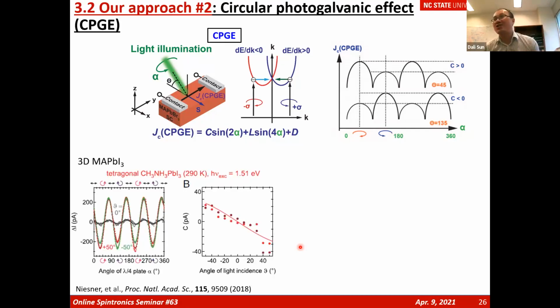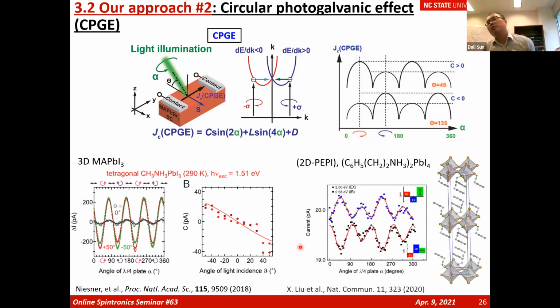And people use this method. Actually, the same author published in the PNAS publication in 2018 and demonstrated there is a possible split state in MAPbI3. They call it the Rashba circular photogalvanic effect. And Utah's group, Valy Vardeny's group, also proved that in two-dimensional hybrid perovskites, where we have symmetry breaking due to the quantum well effect, they form a typical Rashba effect. You're able to see continuous-wave circular photogalvanic effect and transient circular photogalvanic effect giving you terahertz emissions. But again, this is a two-dimensional material, it's not MAPbBr3. As we said in the first report, the Rashba state was demonstrated in MAPbBr3, but there is missing evidence of CPGE responses in MAPbBr3.